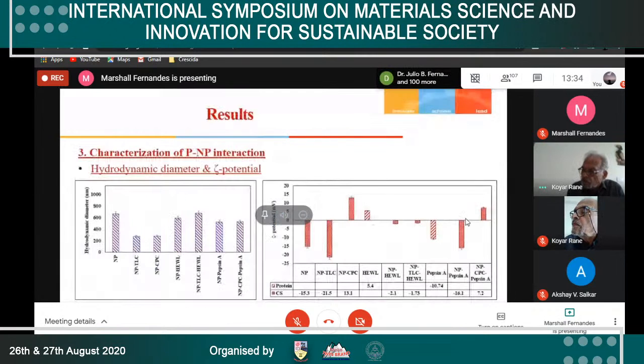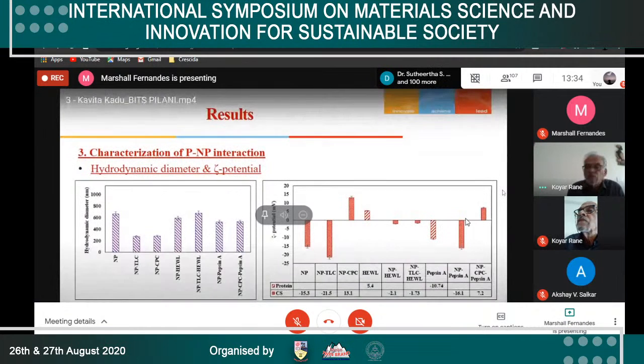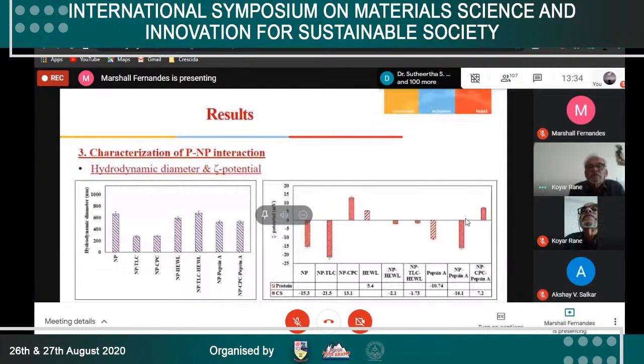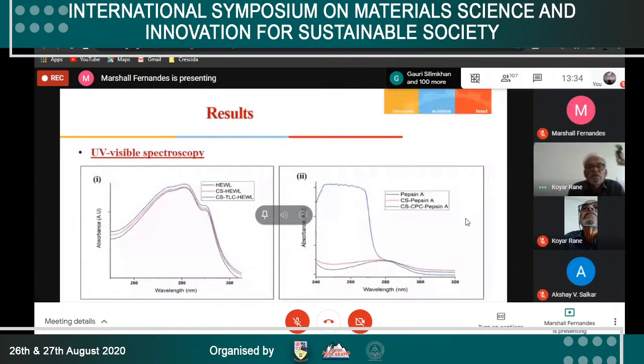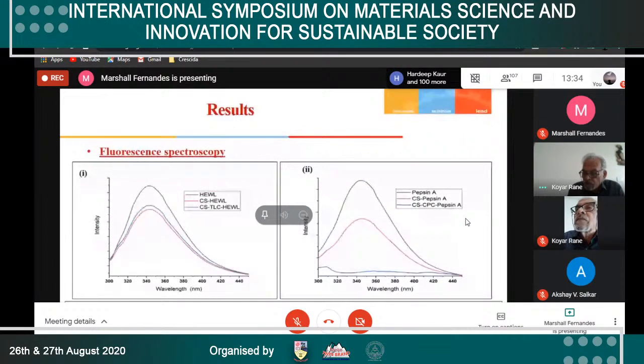After incubation with proteins, an increase in the hydrodynamic diameter and a change in the zeta potential values was observed, indicating the adsorption of protein on the NP surface, leading to the formation of protein-nanoparticle conjugates. Native proteins exhibit characteristic maximum absorption at 280 nanometers due to the aromatic amino acids. This absorption intensity was seen to increase in both cases, which is indicative of protein binding on the NP surface. A decrease in fluorescence intensity was noted for nanoparticles upon interaction with lysozyme. Similarly, unfunctionalized nanoparticles upon interaction with pepsin decreased the fluorescence intensity, but a major quenching was seen for CPC functionalized NPs upon interaction with pepsin, which suggested conformational changes of proteins.